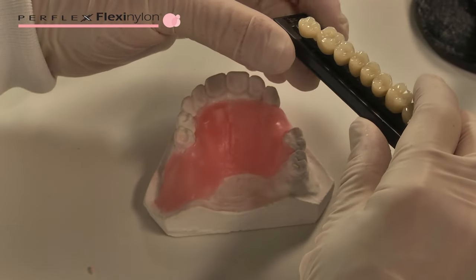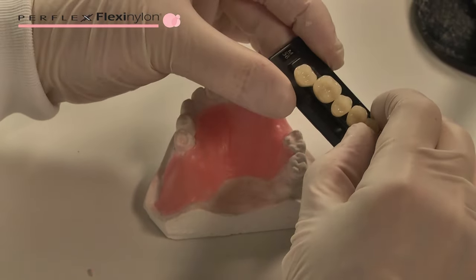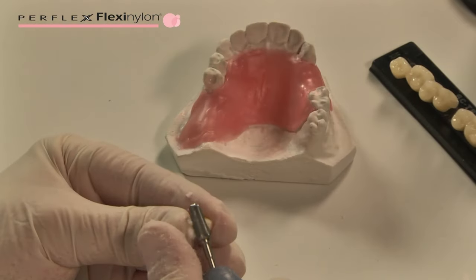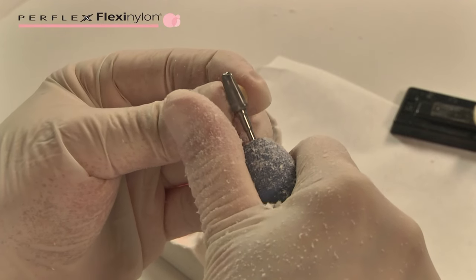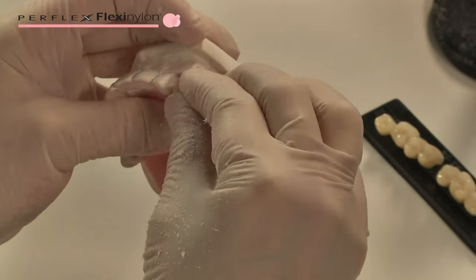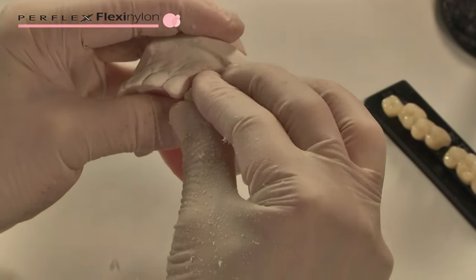Setup: Use acrylic artificial teeth. Avoid the use of composite artificial teeth, which can break under injection process pressure. Grind the acrylic teeth only as much as necessary, leaving enough room for the thermoplastic denture base material to attach the acrylic tooth and large enough for the retention holes.